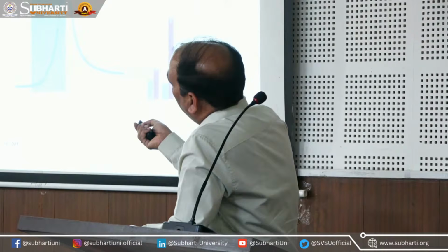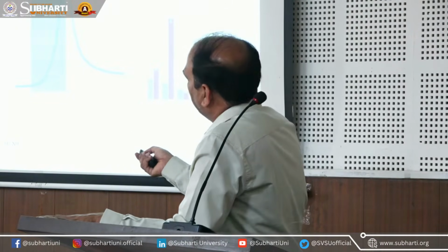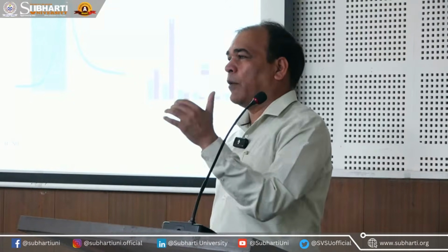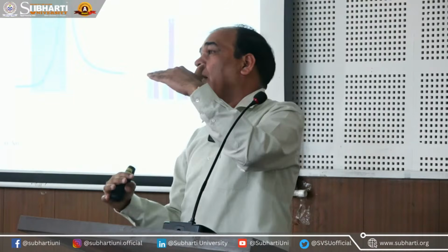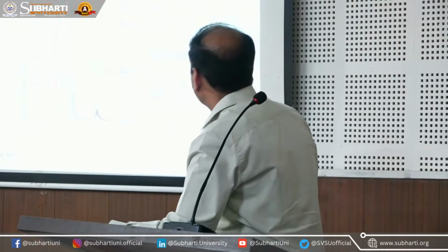The thickness of the sample also plays a crucial role. Even just changing the thickness while keeping all other parameters the same shows a different result. This means thickness is also a crucial parameter, because when the gases interact over the surface, up to what depth it is changing the resistance needs to be measured, and it is also showing the NO2 response.